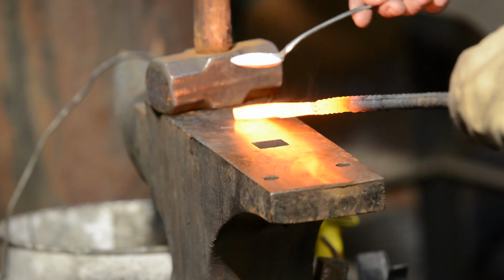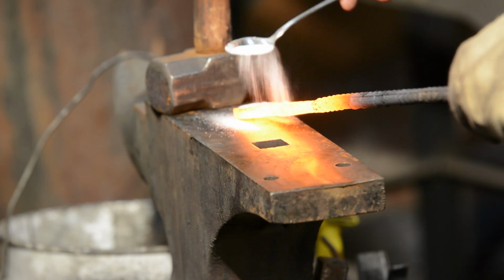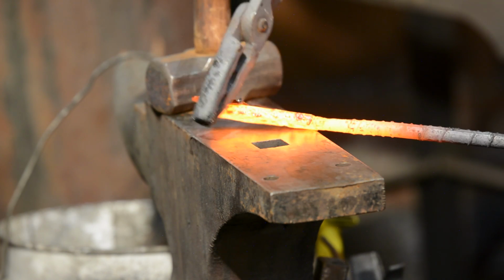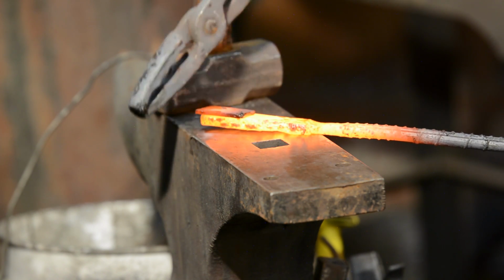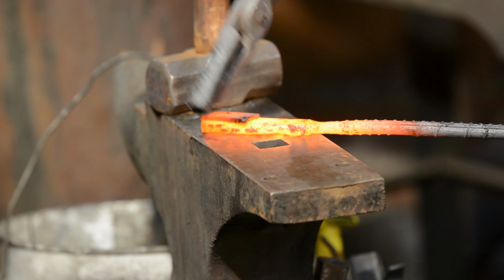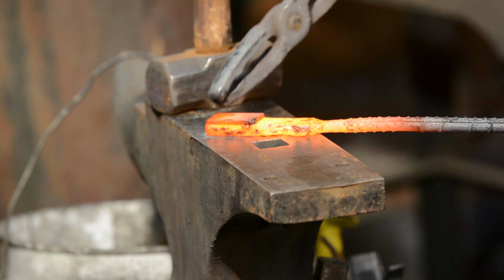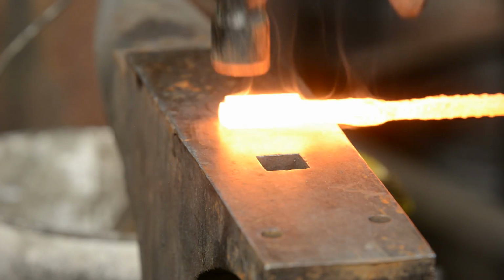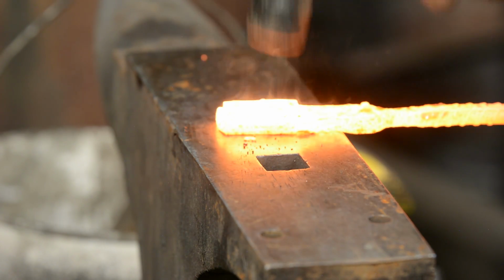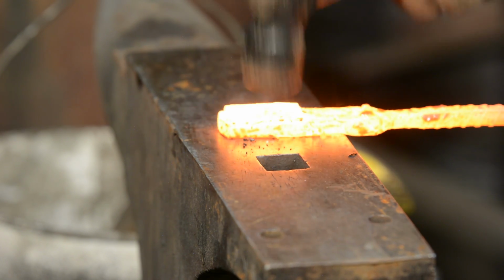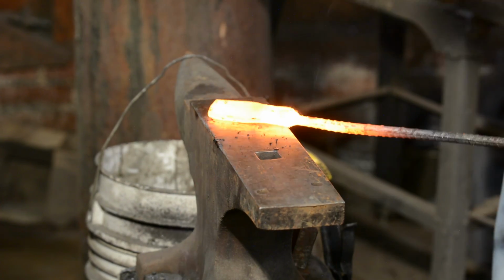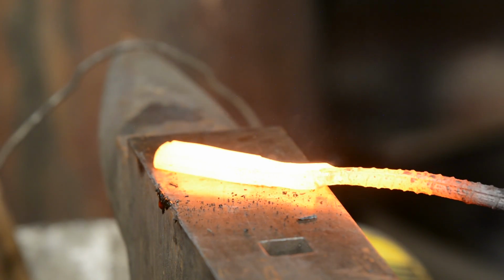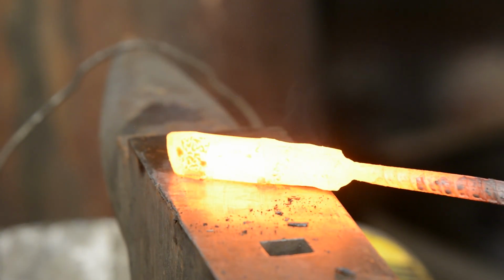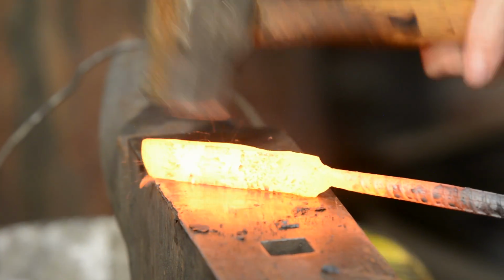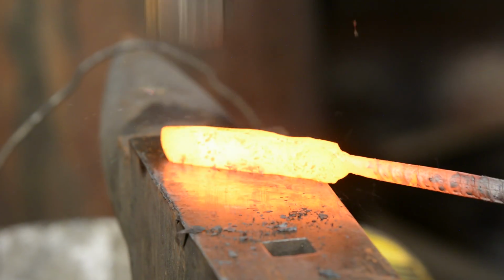Then I fluxed it up with anhydrous borax, heated it to about 2400 Fahrenheit. A few taps and it fuses into one solid block of steel. Back into the fire, then I draw it out about 6 inches long, 1/4 inch thick, and a little over 1/2 inch deep. Normally I'd use my hydraulic press to draw it out, but sometimes it's fun to just go at it with the hammer.